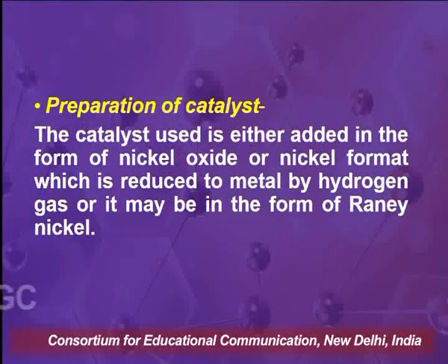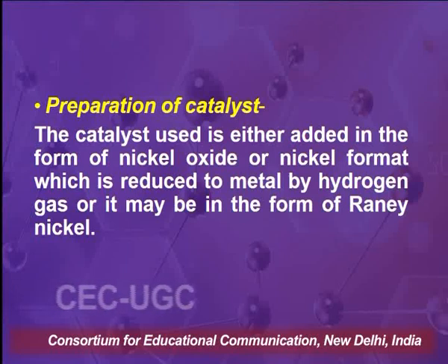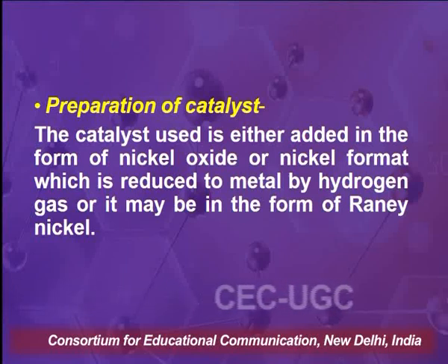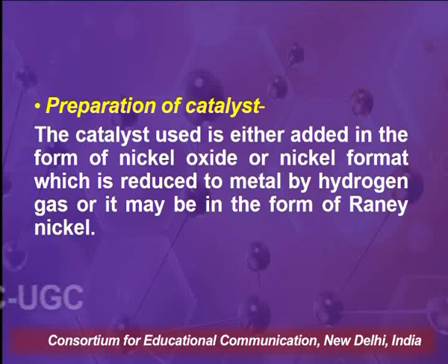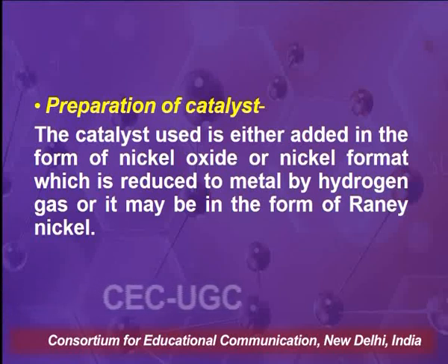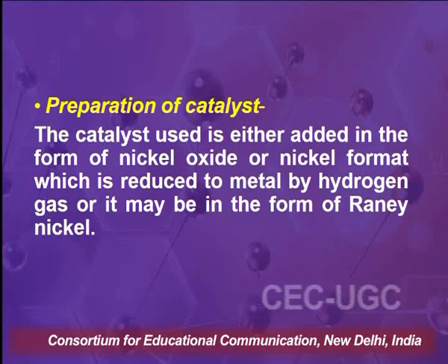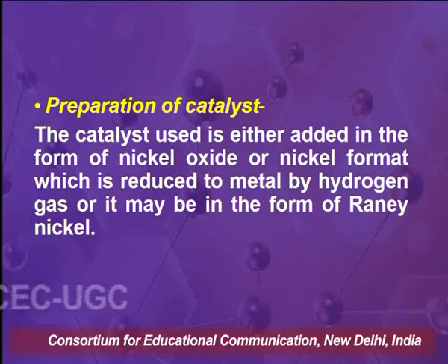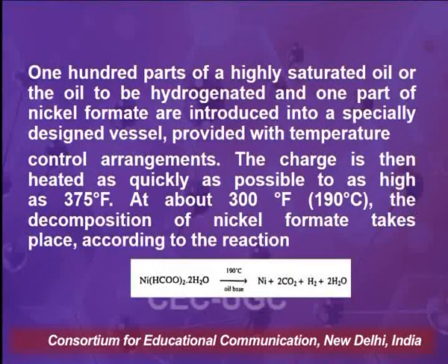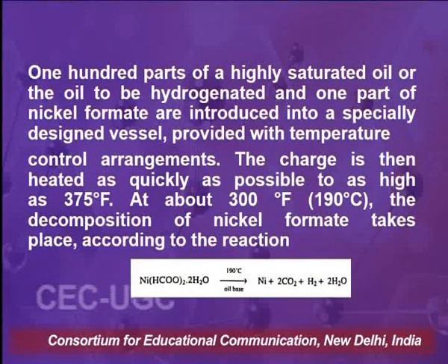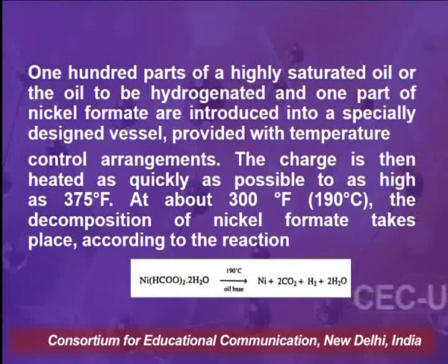Now, the third point is the preparation of catalyst. First was the purification of hydrogen, second was the purification of oil, now it is the preparation of catalyst. The catalyst used is either added in the form of nickel oxide or nickel formate, which is reduced to metal by hydrogen gas, or it may be in the form of Raney nickel. 100 parts of a highly saturated oil or the oil to be hydrogenated and 1 part of the nickel formate are introduced into a specially designed vessel provided with temperature control arrangements.